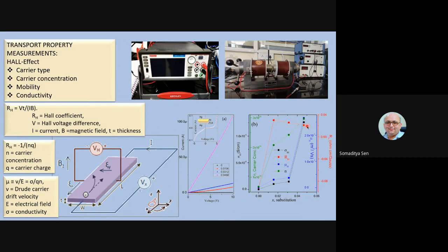What is interesting is that it is not necessarily true that if you put more gallium you get more p-type. The p-type nature has decreased in the case of high concentrations of doping. So what can be the cause? There can be many causes, because gallium is 3 plus, so it is substituting zinc in the 2 plus state. So they either generate oxygen, sorry, zinc vacancies, which can be a source of the n-type nature. So all these types of things are there.